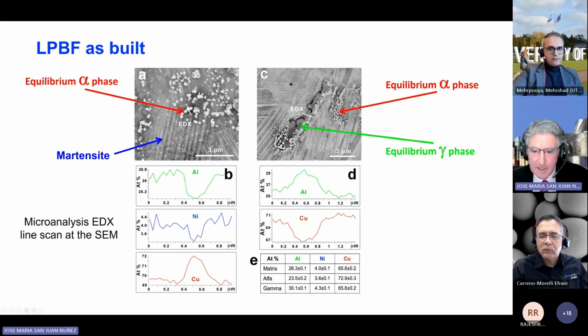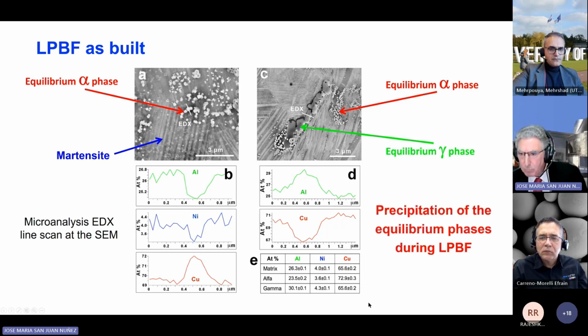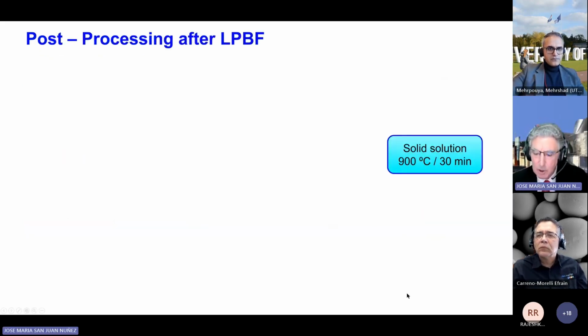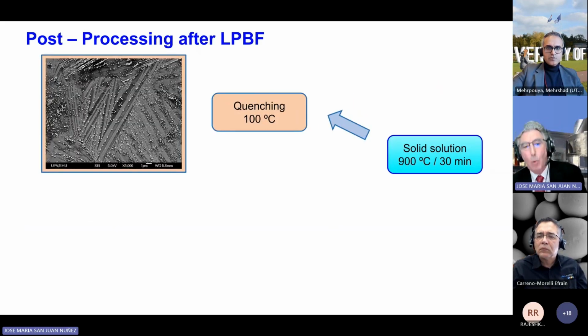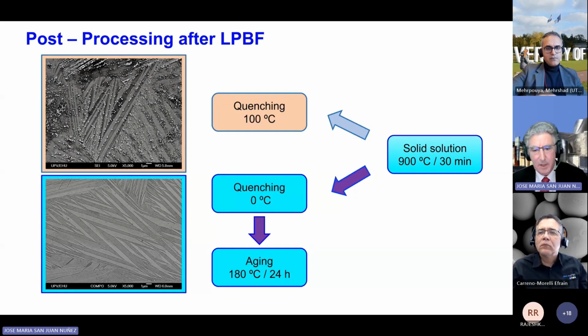Not only the line scan, but we have also measured the concentration point by point of the different phases and the matrix, and then we can identify that the precipitation observed corresponds to the precipitation of the equilibrium phases during the laser powder bed fusion. As I commented, this is important because this will destroy the behavior of the material, and then we have to do a solid solution. Even if we do a slow quench at 100 degrees centigrade, we can still get precipitates. But if we quench at 0 degrees centigrade, and then we can do an aging to control the atomic order, we can get a fully transformed material in martensite and absolutely precipitate free.